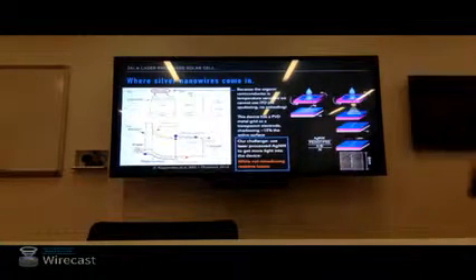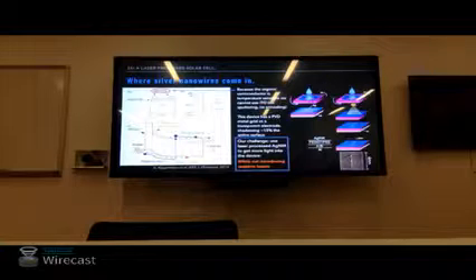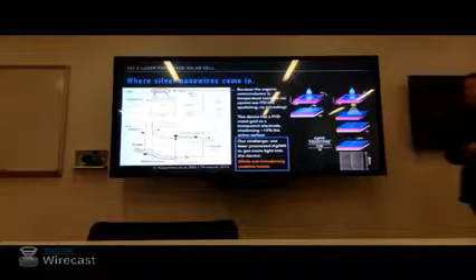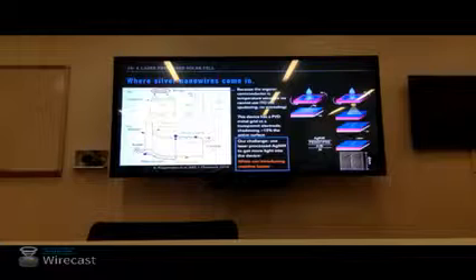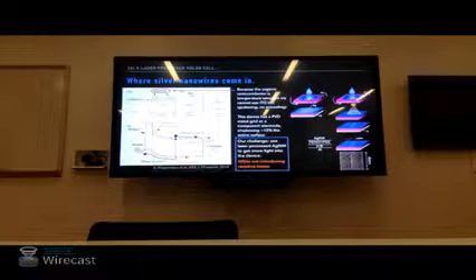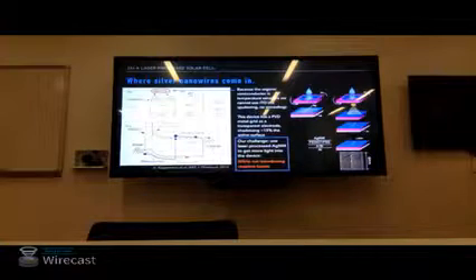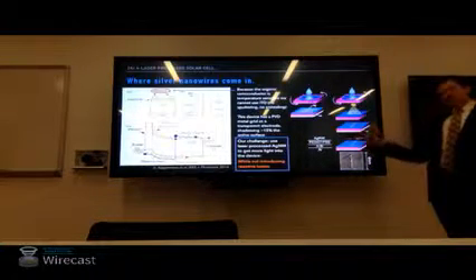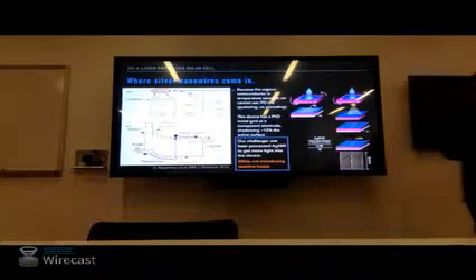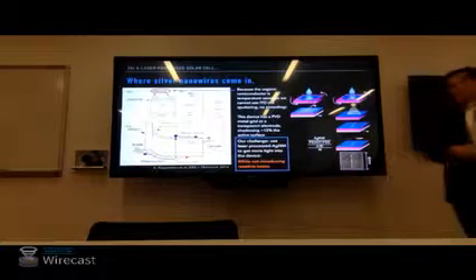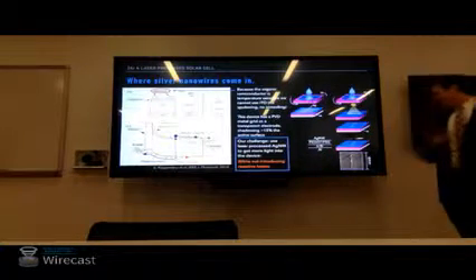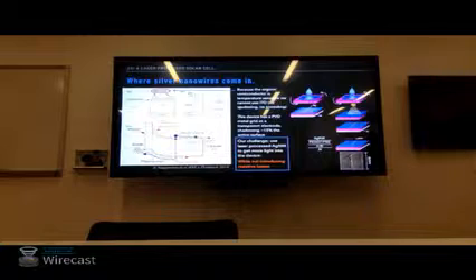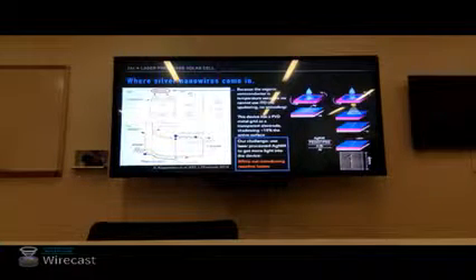We propose this sort of processing scheme where we start again with spin coating the PEDOT:PSS, our organic semiconductor. Then we'll spray coat the silver nanowires. We're going to still have a physical vapor deposition step, mostly for the back electrode, but also to have a contact point for testing, so we'll put a contact bar on. Then we'll use our laser. And this is a picture of what a device looks like after it's been made.